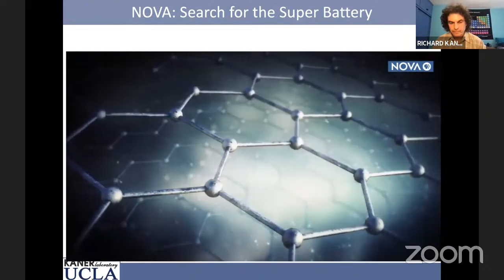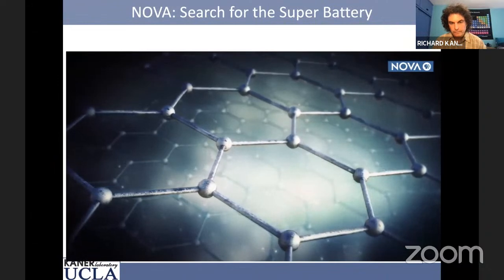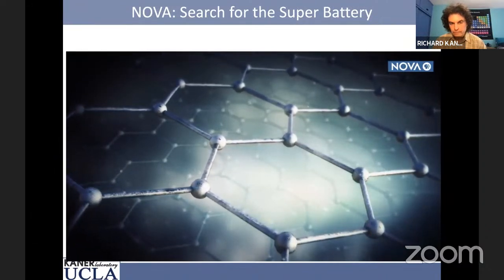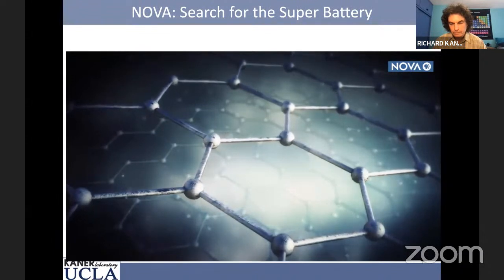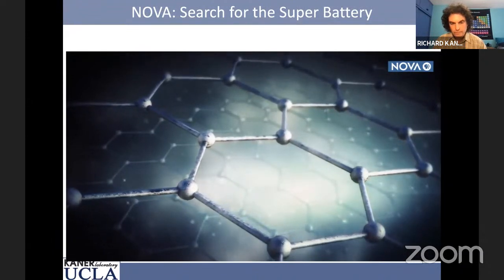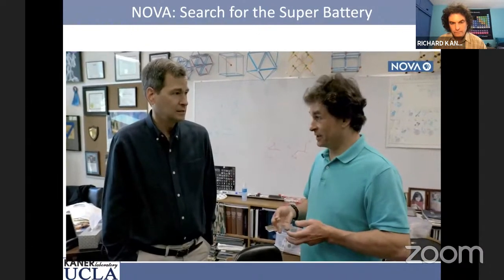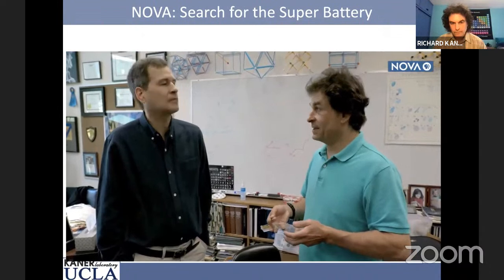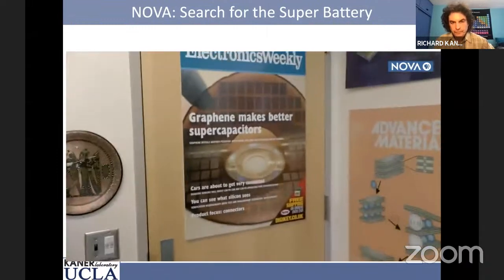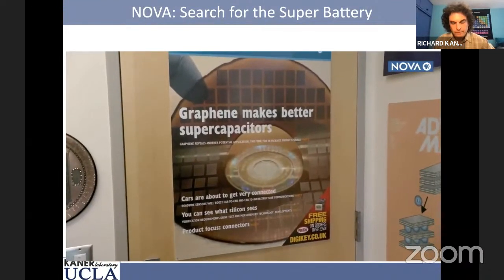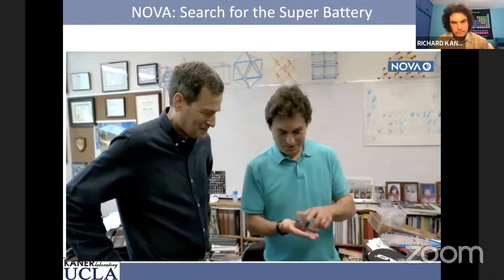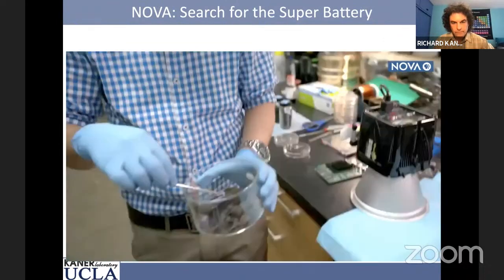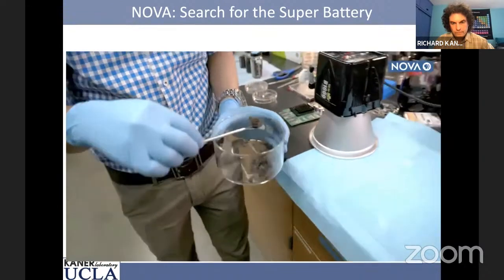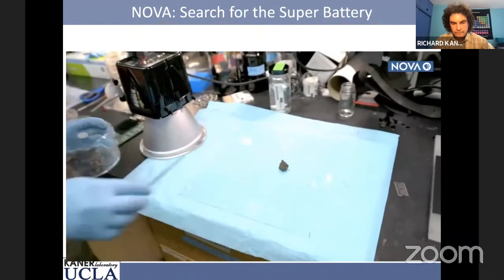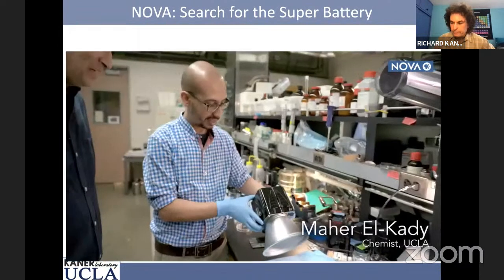Graphene is the strongest material ever tested. It's a layer of carbon that's 1 atom thick, giving it extremely high surface area. Kaner says 1 gram of the stuff would cover 4 football fields. Graphene provides the high surface area and conductivity necessary to store large amounts of charge. Which means graphene might just allow supercapacitors to be even more super. And Kaner's lab has come up with a surprising way to make it. It starts with plain old graphite. This is a chunk of graphite oxide that was mixed with water and then freeze-dried. Maher El-Kady hits it with an ordinary camera flash. Big flash. Yes, big.